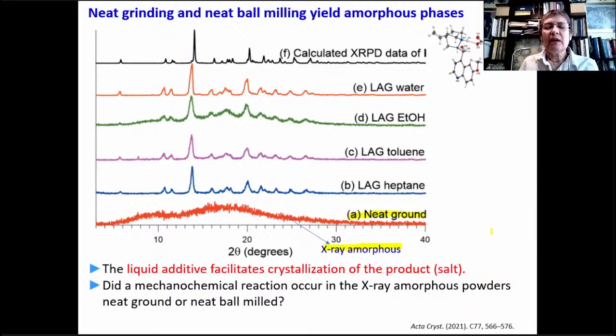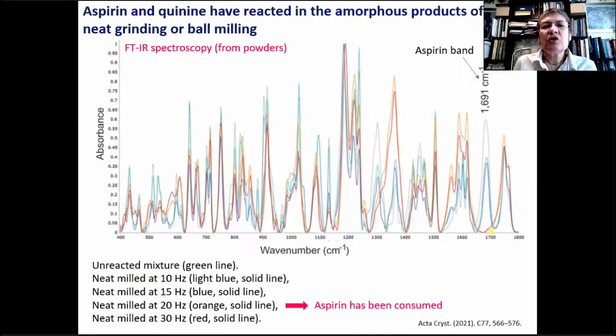Okay. So a research question at the time has been, did this amorphous material actually contain a mechanochemical product, or was it just the physical mixture of the reactants? It could be obtained by grinding manually in a mortar and pestle, or also by neat ball milling at different milling frequencies. So we studied these amorphous phases by infrared spectroscopy and by microcrystal electron diffraction.